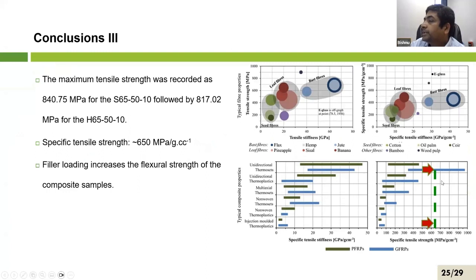So when we compare the properties of the material that we got, we found that the specific tensile strength falls within the range of these glass fiber reinforced composite materials. So it's almost a direct, mechanically almost a direct substitute. Wow, that is impressive. It lies in between the glass fiber reinforced unidirectional thermosets. They can range from somewhere between 350 all the way to 950. And we were somewhere around 630, 640. So it's in between there. Impressive.